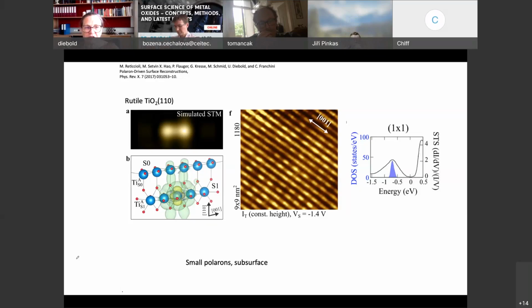Okay. This is a collaboration with Michele Reticcioli, Cesare Franchini and Georg Kresse. The theorists put the electron into the sample. So this is a row of titanium atoms at the surface, and a row of titanium atoms in the next layer down. If they put in extra electrons that come from this vacancy, the most favorable condition is here, underneath, in the second layer. And there's a little bit of density of states reaching out. These are simulated STM images of one extra electron in the second layer. You see this double lobe feature. These are simulations of the electrons in the filled states, these gap states.